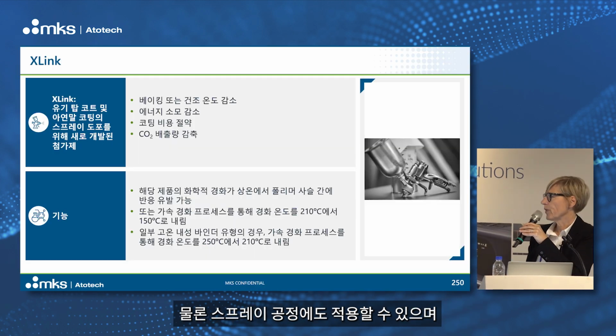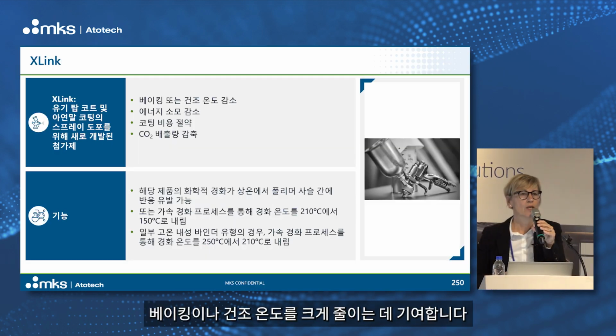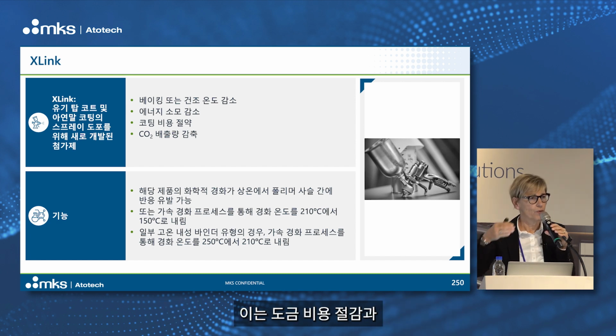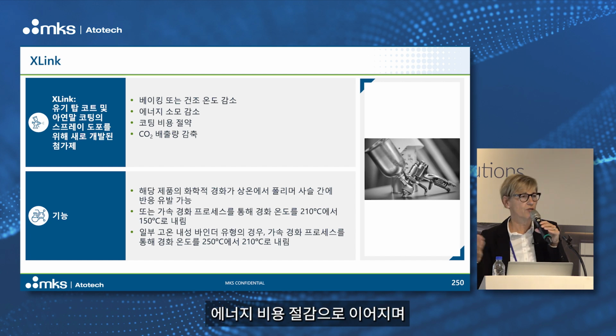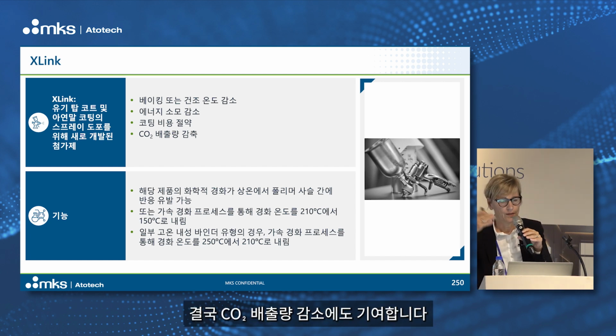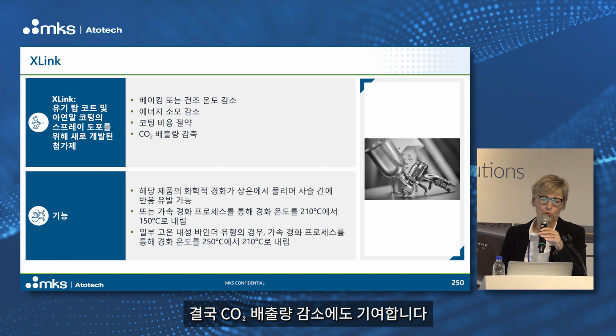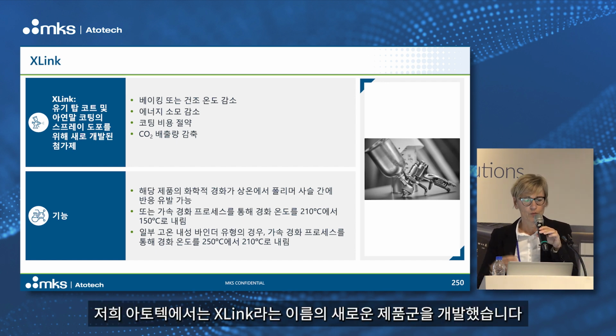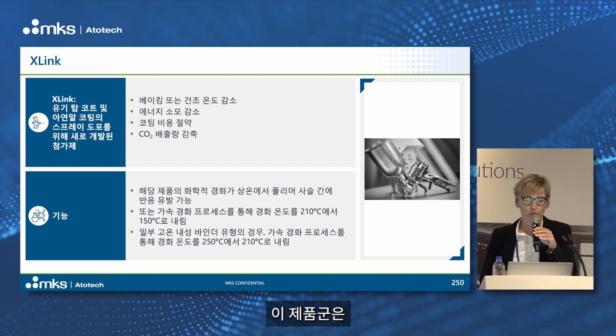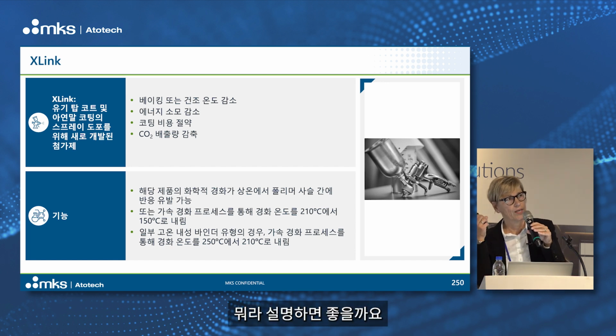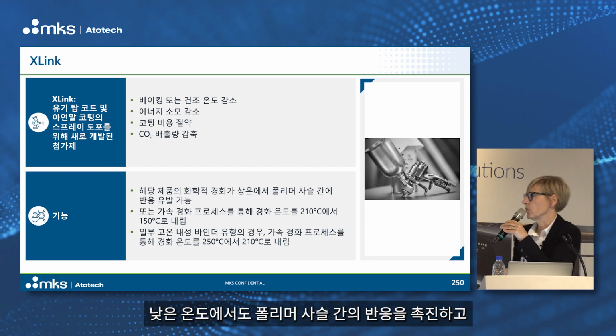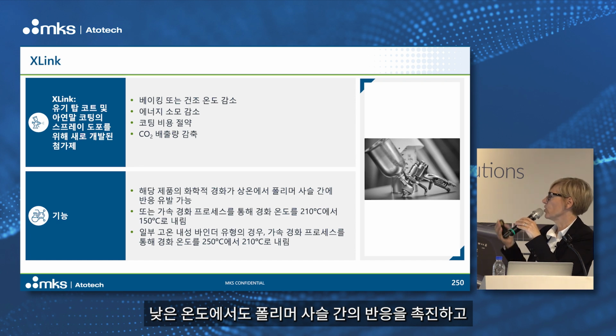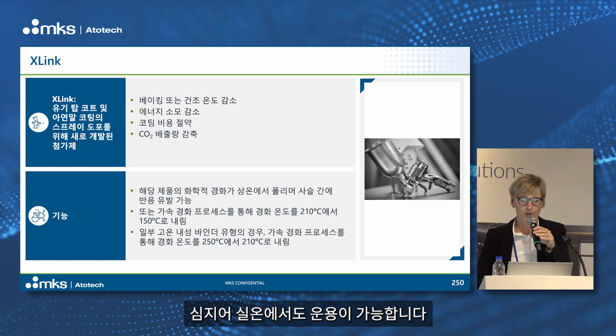And of course, also for spray applications, you can do a lot in reducing the baking or drying temperatures, and that will always pay into the coating cost reduction, energy consumption cost, and of course, into the CO2 emission. We have developed a new family of products under our X-Link family name, which helps to trigger the reaction between polymer and polymer chains at lower temperatures, even at ambient temperatures.